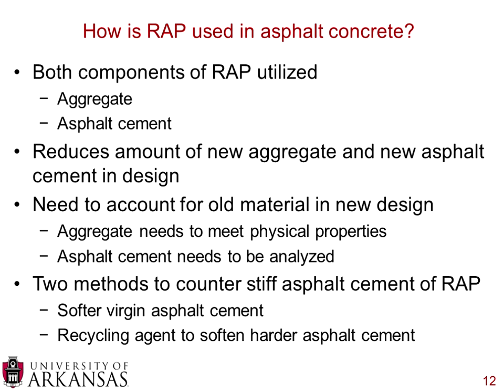Now, asphalt cement off of RAP, we talked about earlier, is generally highly oxidized. It's stiffer. It's gone through perhaps some steric hardening. It's lost some of those oily compounds. So sometimes you need to counter the stiff asphalt cement that's found in RAP, and you can do this in one of two ways. You can either use a softer virgin asphalt cement than what you would normally use in a mix, or you could use some sort of recycling agent to soften the harder asphalt cement.